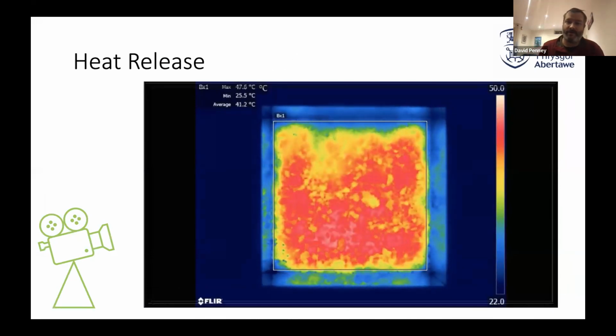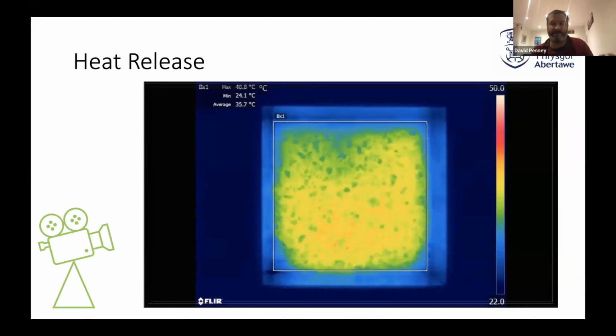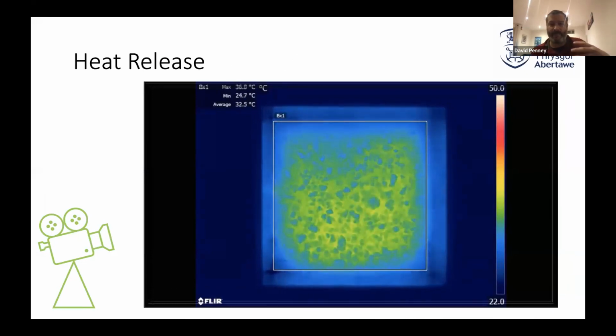So what you can do is impregnate this vermiculite with this salt, and when it's dry, or you can dry it out using waste heat. You can take this wet vermiculite to a factory which is kicking out loads of waste heat, dry it out, and that's then storing that heat. When you want to release the heat, you blow cold, moist air through it. The moisture will activate the salt in the matrix and will give out heat.